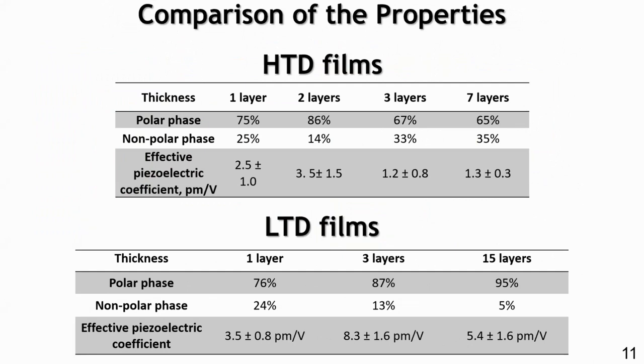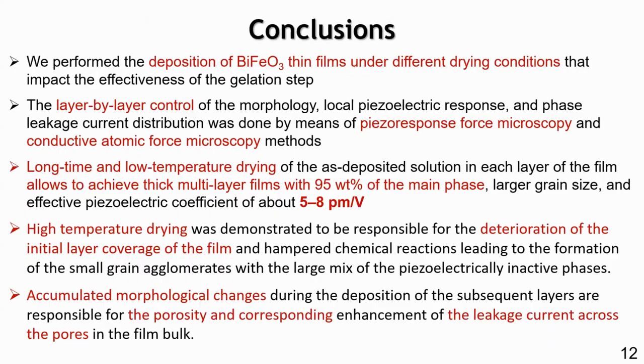So this is a comparison of these two sets of films. You may see that in the low temperature dried films, we have a great enhancement of the fraction of the polar phase in the thick films, and we have an increase of the piezoelectric coefficients many, many times. So in conclusion, we tried to understand how the morphology of the films and the preparation process of step-by-step deposition influence the final properties of the BFO films. And we found that layer-by-layer control of the morphology is really important to understand what phase distribution happens during the process of material deposition.